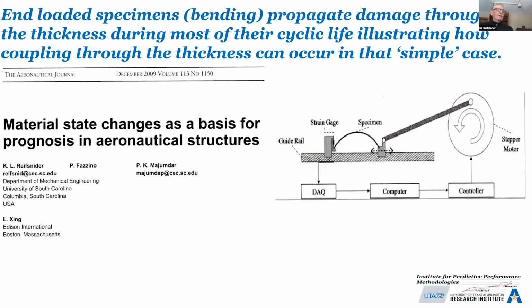Well, here's an experiment run by Fazzino, and he said, well, all right, I know where the failure is going to be if I bend this specimen until it fails in fatigue. It's going to fail in the middle of the specimen. So I can follow the failure plane as it develops through this test. We're going to run this thing until it fails, and we're going to try to follow the development of the fracture plane. That's what we're sort of focusing on here.